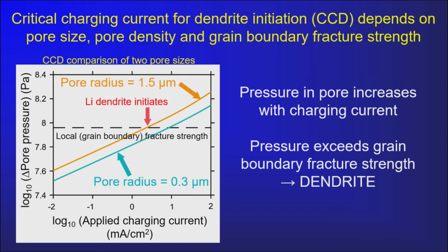On the left, you see a plot of the pressure in the pore versus the applied current. And these are the two modeled pressures as the current increases. The dotted line is taken experimentally from the grain boundary fracture strength. So experimental data goes into the model, like the pore size, which we get from SEM, the distribution of the pores, etc. This is also from experiment. The model then calculates the relationship between pore pressure and applied current.